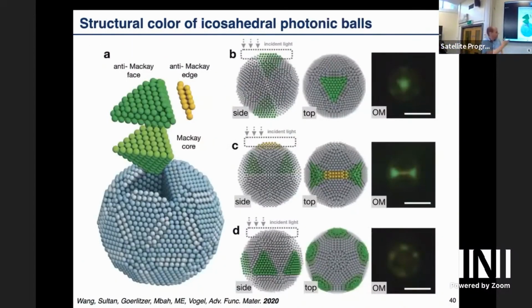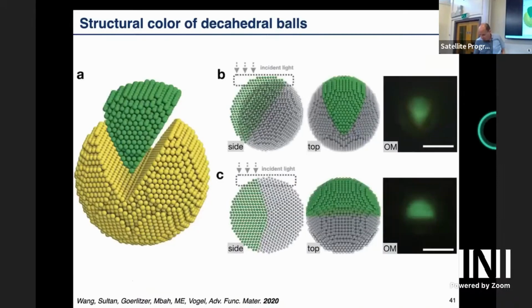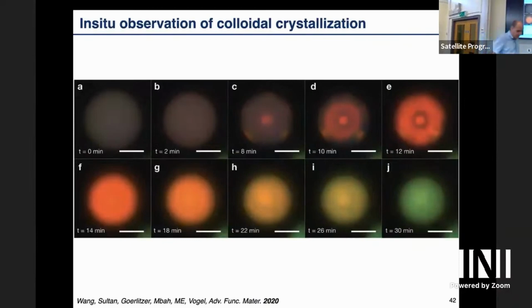And if you're interested in photonics, we have a paper about how the color appears and how you get the different characteristic signatures of the clusters. You can do that for the decahedral, and for the icosahedral. Plus, you can use these light microscope techniques to look at the evolution of the cluster. So here's time. This is an in situ observation of how this cluster forms. It starts from a liquid, no color, or just grayish color, and then it goes through the process.